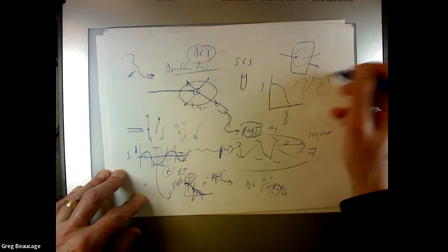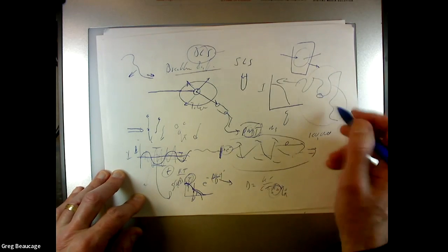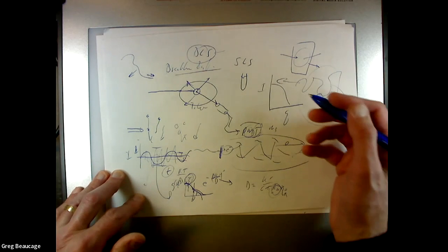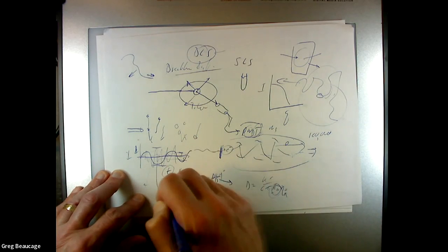So if you're looking at a polymer, it's got local relaxations on the chain, and the whole thing moving around has a relaxation time, and then whatever conformational relaxations. You can pick all those out with curves like this from different machines that are basically the same idea: see the squiggly curve, transform it, get this decay curve, and get the relaxation time out of it. So I'll go into that in more detail. It's worth spending some time looking at that.